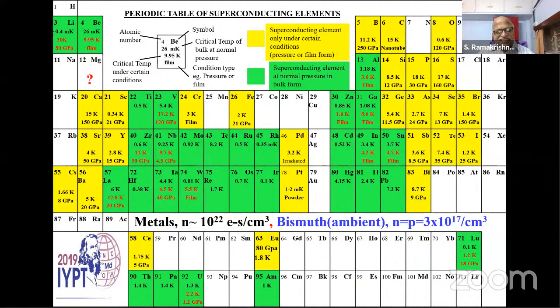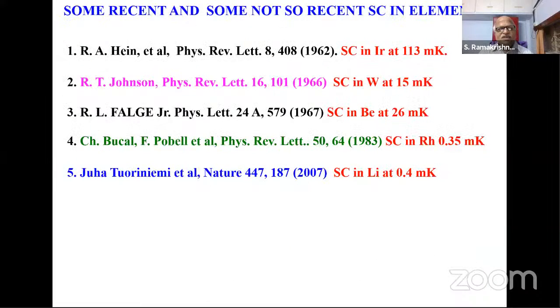So with this in mind, we decided to look for superconductivity in bismuth, and I will explain why it is so important. As I told you, once mercury started superconducting, people looked at all the elements of the periodic table, and some found success. But as the TC, the superconducting transition temperature, goes lower and lower, things became a little difficult. For instance, iridium is superconducting at 113 millikelvin, then tungsten at 15 millikelvin. Beryllium, because of its toxicity, we couldn't purify; it was later found to be a superconductor in 1967 at 26 millikelvin.